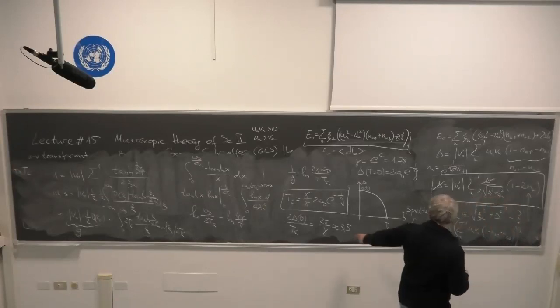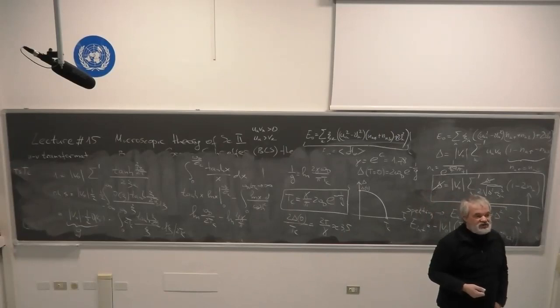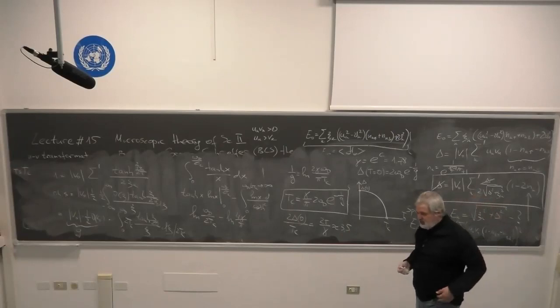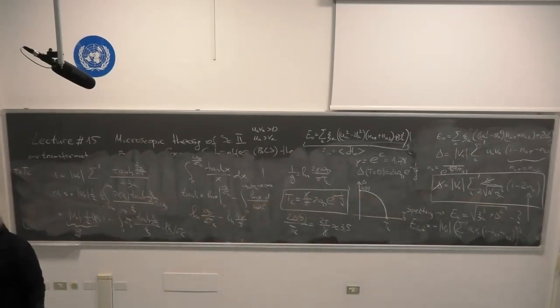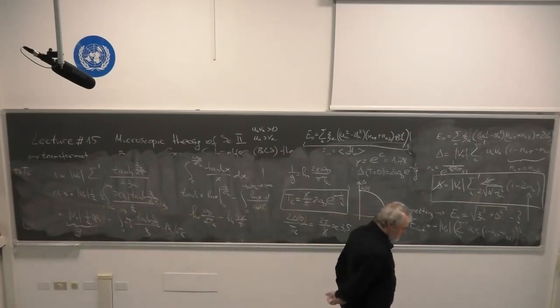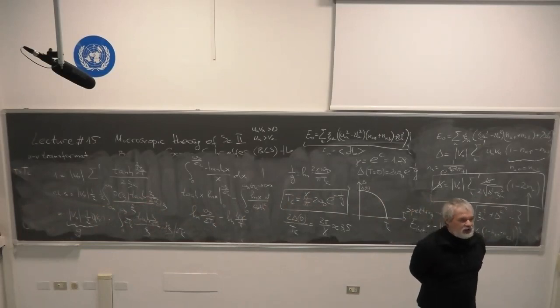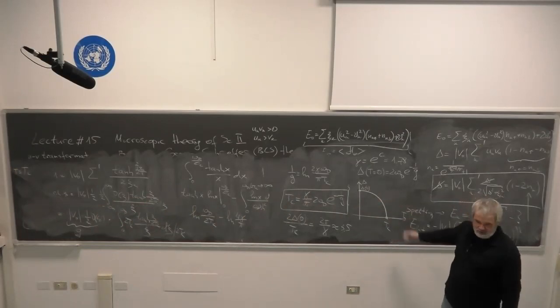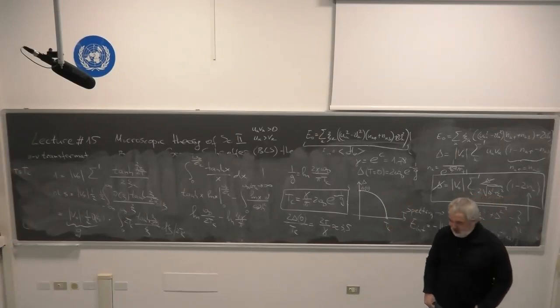The measurement of 2 delta and the ratio of 2 delta to Tc showed a number which largely deviated from 3.5, which says that the mechanism of high temperature superconductivity was probably not related to electron-phonon interaction, and moreover, BCS theory probably does not describe high temperature superconductivity. However, all conventional superconductors, mercury, tungsten, aluminum, niobium, nicely fit electron-phonon interaction and BCS theory.